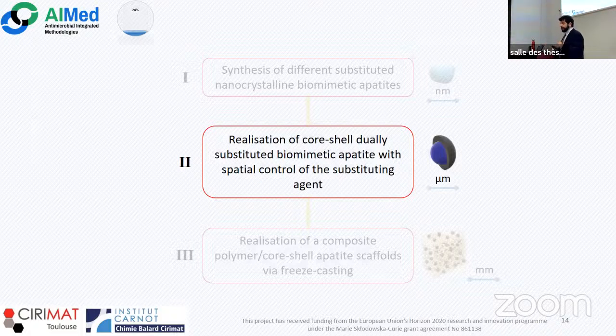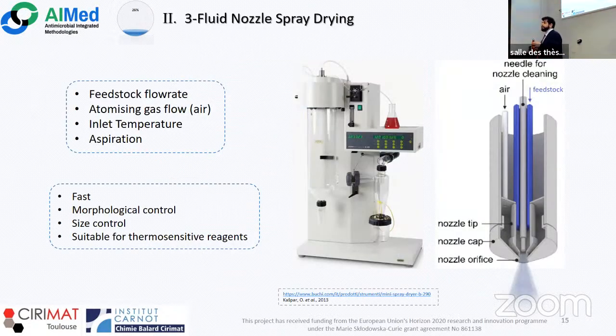Then we can go further and study the realization of the core shell particles. To do that, we started to look at the spray drying technique. The spray drying technique is as simple as the name says. We have the spraying of a solution and the drying at the level of the nozzle, here and here in the real machine. Then the particles, which are exposed to a high temperature for a fraction of a second, go through the drying chamber and then get aspirated and separated in the cyclone, where we can collect the powder at the end. The whole process is very fast and can grant a control of the morphology and of the size of the particles.